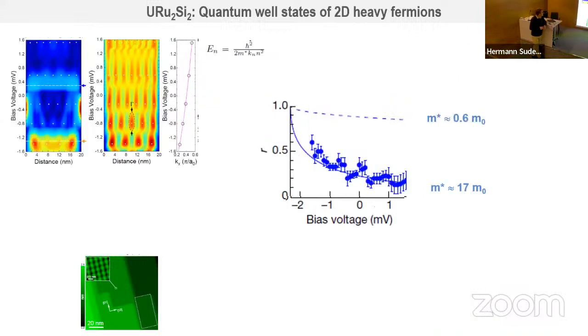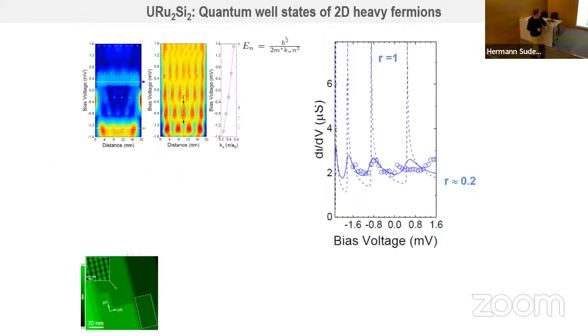You can also ask yourself what is the reflection coefficient, because of course there is some reflection on the borders of the terrace, and you can trace the reflection as a function of the energy. This is what you would get for copper, for example, and this is what you get for a heavy fermion like this. So it's something which works nicely. You can also make a scan here in the middle and see how the conductance changes with the bias voltage, and see that it corresponds to what you expect for the reflection coefficient, which we have been showing in the previous transparency. So these things work pretty nicely.